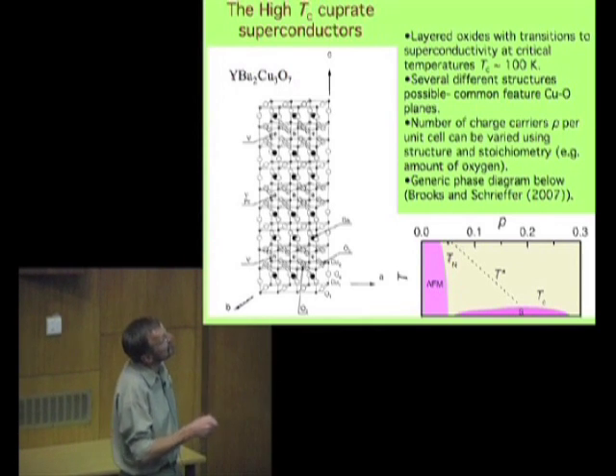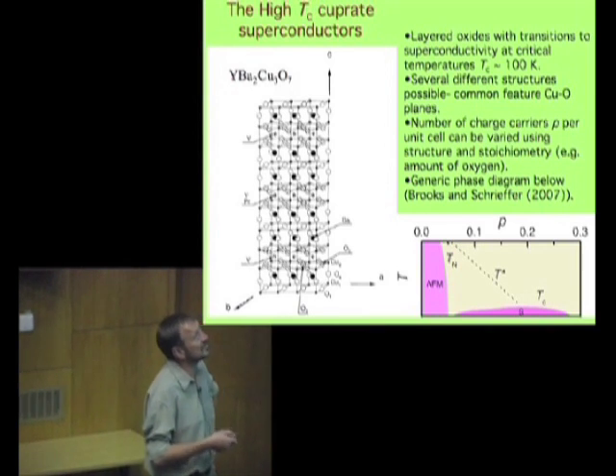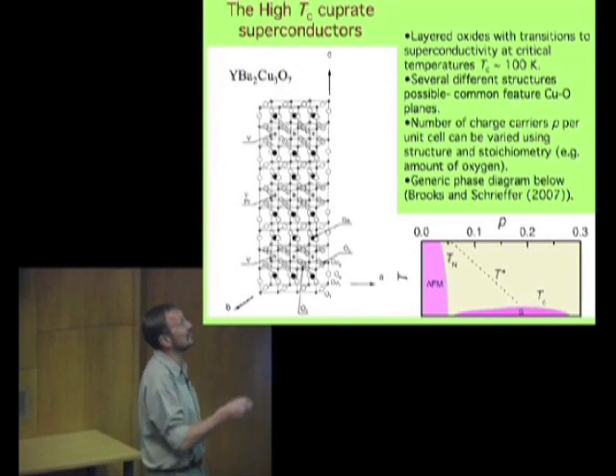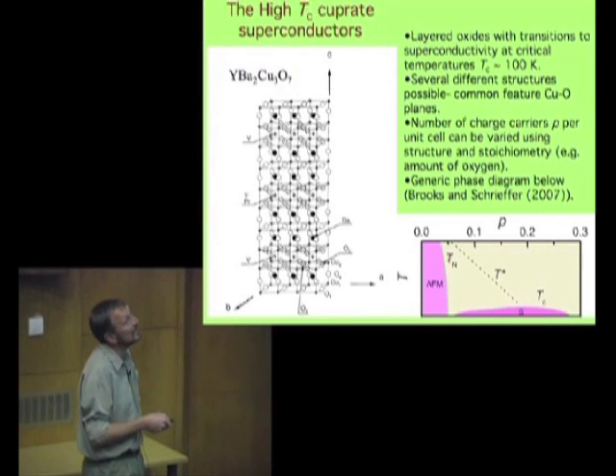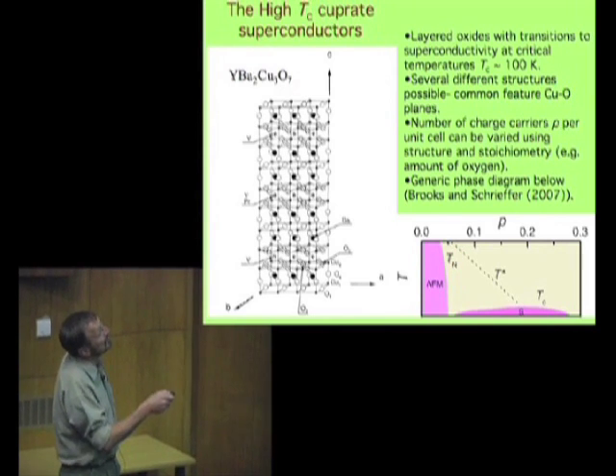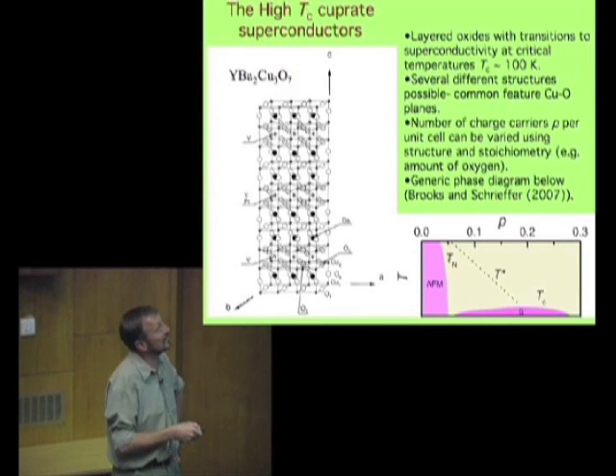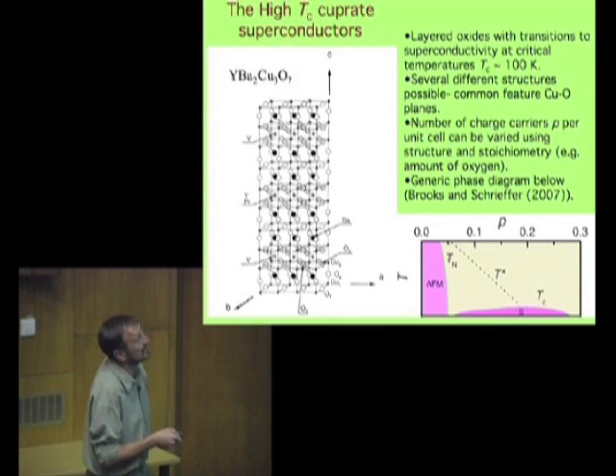And you can tune these things over a wide range of carrier densities using structure. By varying the structure, you can make different numbers of layers of these things. And you can also do things like muck around with the oxygen doping. And this gives us a varying hole density in here.